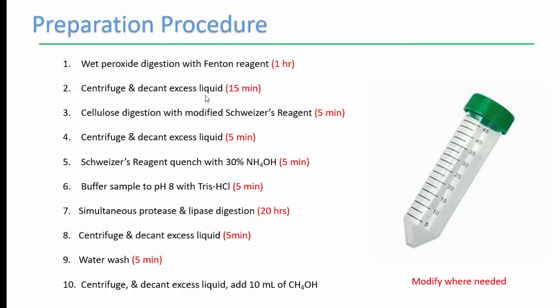So here's the way the procedure would typically go. And depending on the sample matrices you're using, all of these steps may not be necessary. So this is a worst case scenario using wastewater influent. We'll do a wet peroxide with a Fenton reagent for an hour. That's going to decontaminate the sample and remove all the easily oxidizable carbon and lift any biofilm off of the plastic particles themselves, rendering them a much cleaner surface for spectroscopy analysis.